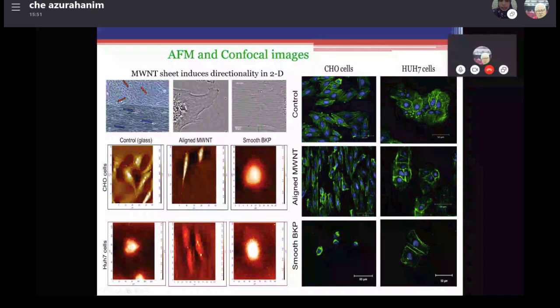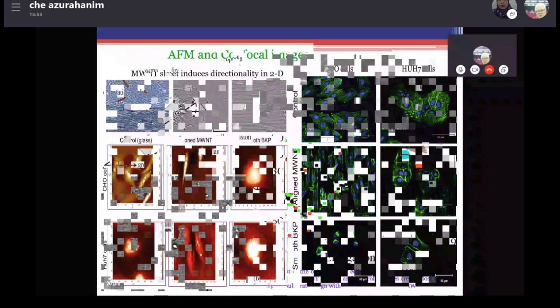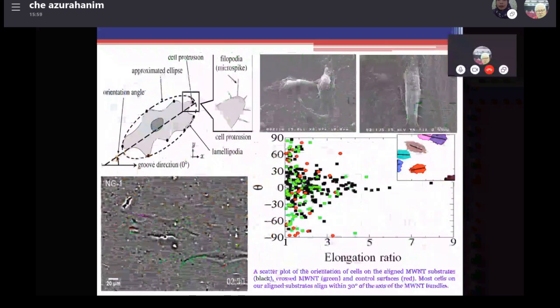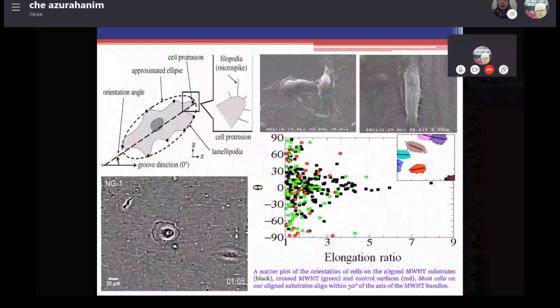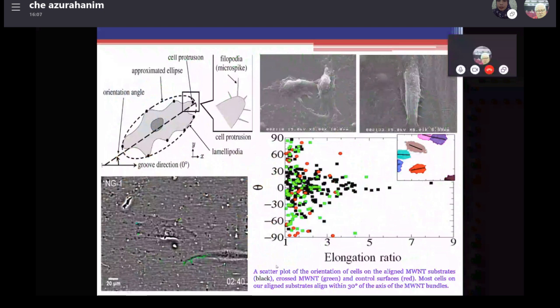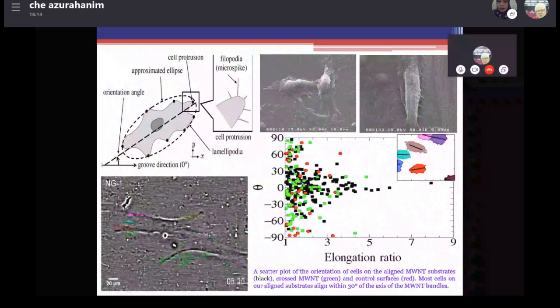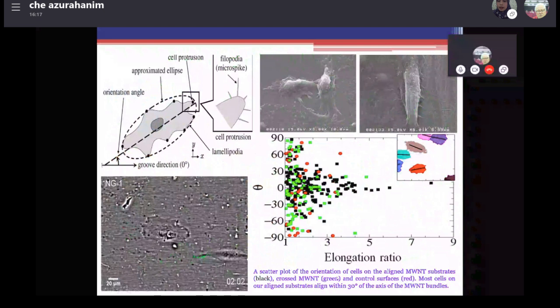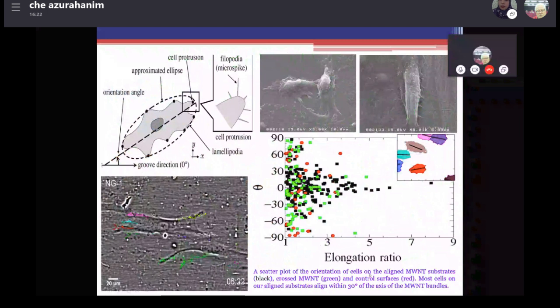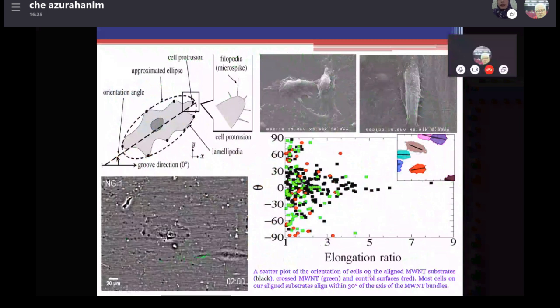Okay, finally we also try to determine at what angle the cells follow the alignment of the aligned substrate. We plot a scatter plot, and from this scatter plot we found the elongation of cells on the aligned multi-wall nanotube substrate, which is the black color, the cross multi-wall nanotube substrate in green, and the control in red. We can see that most of the cells on our aligned substrate align about 30 degrees with the axis of the multi-wall nanotube bundles.